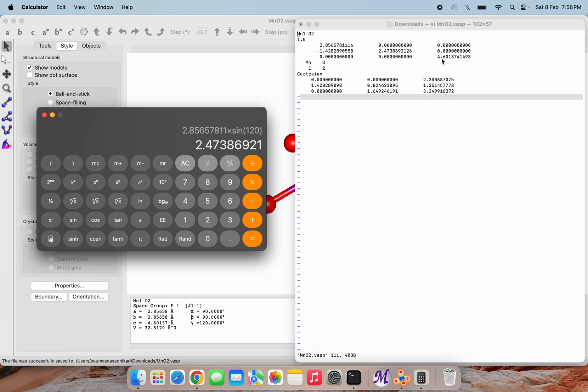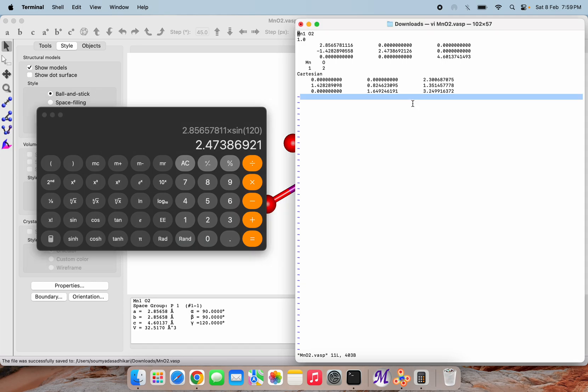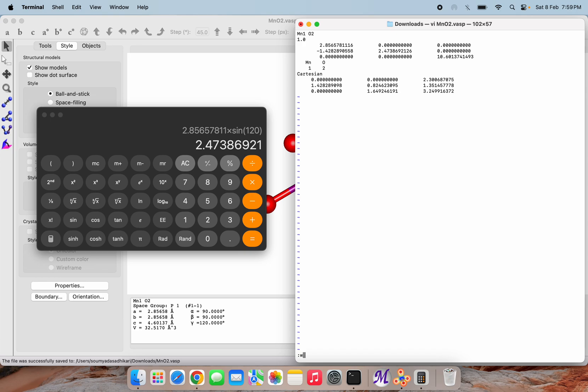Now here I want to extend this lattice along the c-axis so that there won't be any overlap between the monolayers of MnO2. I am going to edit this file. I will only change the z-axis layer value. I am simply making it to 10 point something. Now save this file.